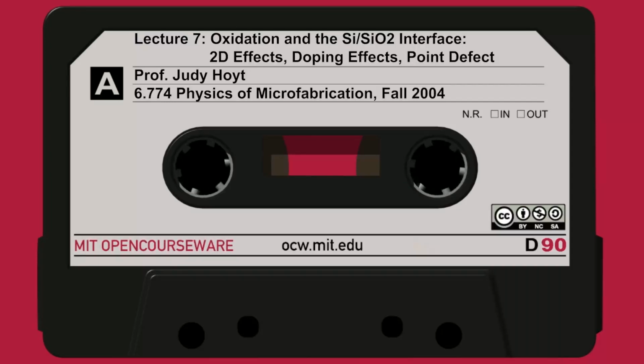That's the simulation. And on slide 19, the upper diagrams are the same as what we just saw. But if we turn to the lower left, SUPREM 4 can actually be used to calculate stress contours. So it's actually calculating the stress in the oxide at each point, and at each point assigning an oxidation rate.